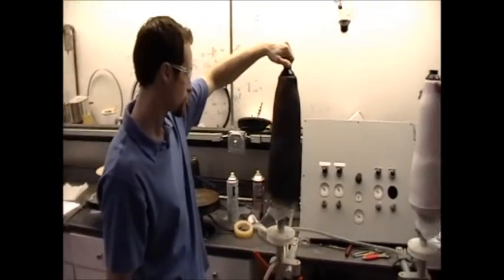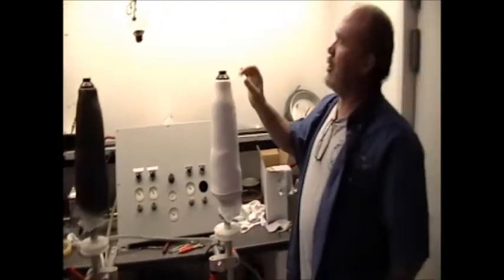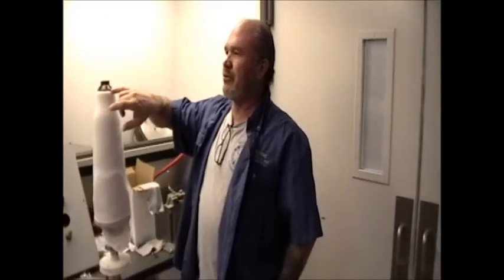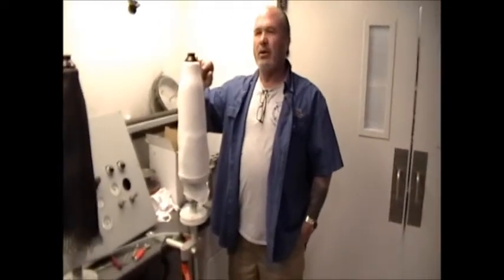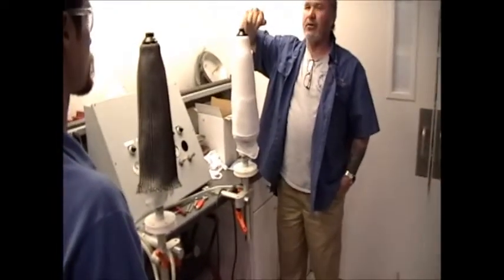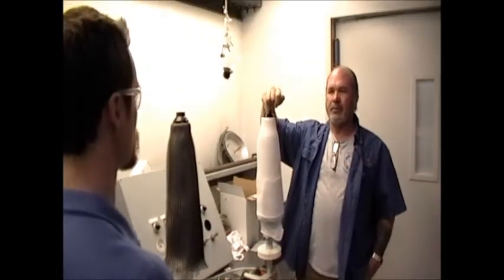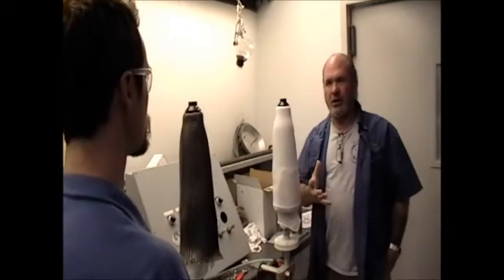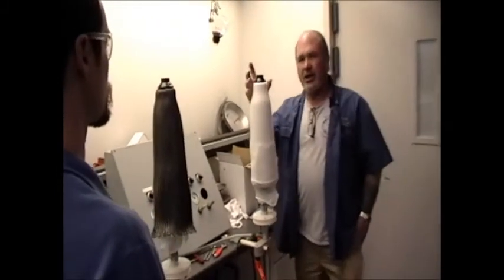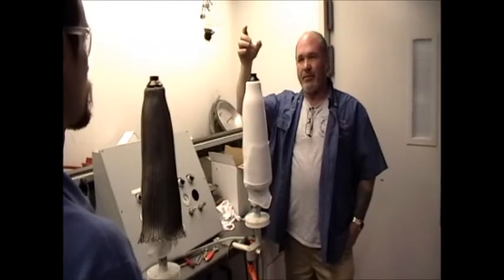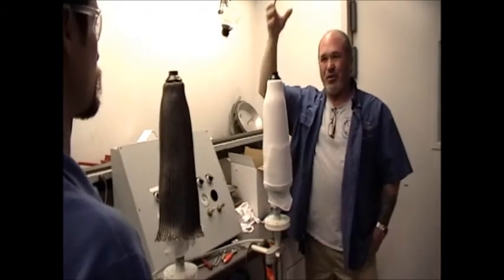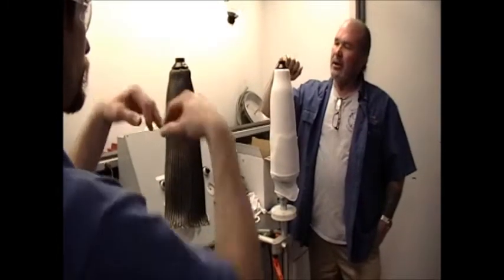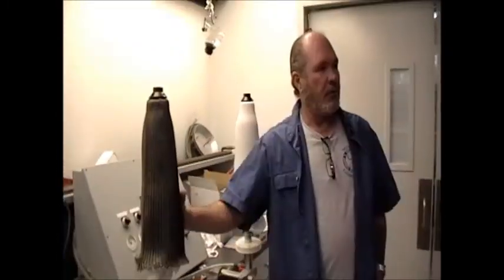Now let's go ahead and, have you got two more bags lined up? Yes. When you pull the bags down, we want to seal it against this edge. That's how you do it. Because when we start pulling vacuum, we want the vacuum to go down through these holes when we pour the resin in. Not around the outside edge. One of the hardest things to do with this lamination is to not touch it when we first pour the resin in. It's very difficult because you want to reach up there and grab it and get started. Right. But we need to wait a few minutes and it's got to flush all the air out. It's got, yeah, exactly. Okay. All right.